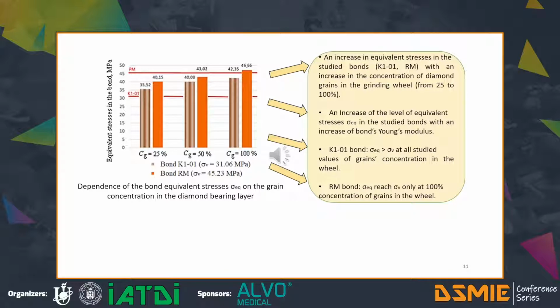The calculation showed an increase in equivalent stresses in the studied bonds, ceramic and glass ceramic type, with an increase in the concentration of diamond grains from 25 to 100%. Equivalent stresses in the ceramic bond exceed the ultimate tensile strength for all studied grain concentrations in the wheel. Equivalent stresses in the ceramic glass bond reach the corresponding tensile strength level only at 100% grain concentration.